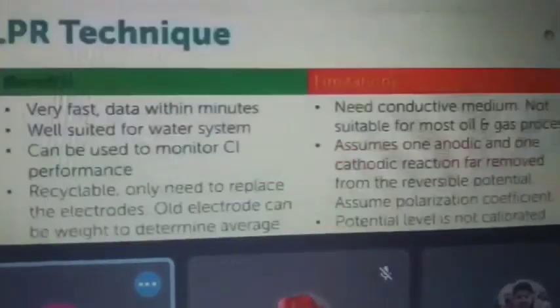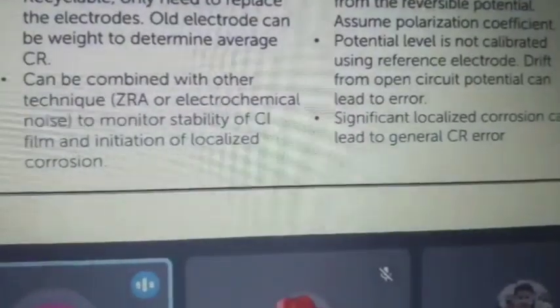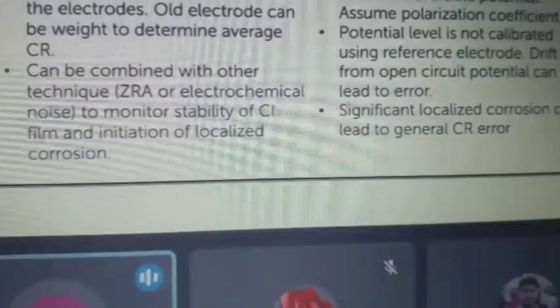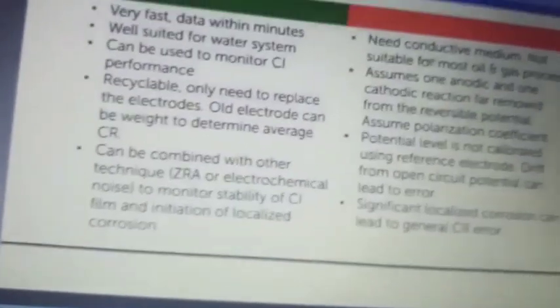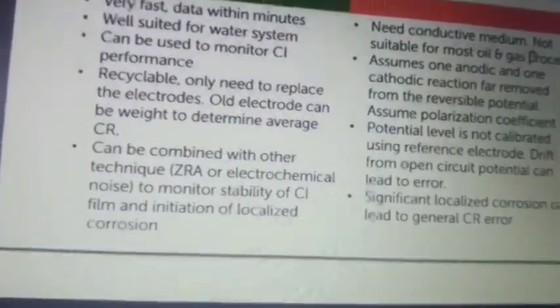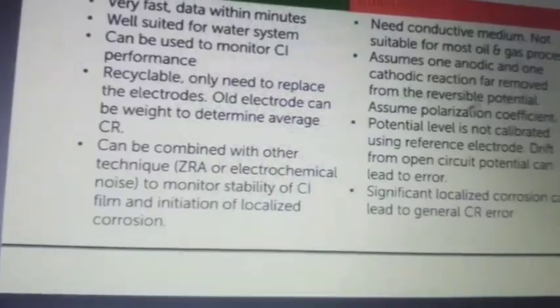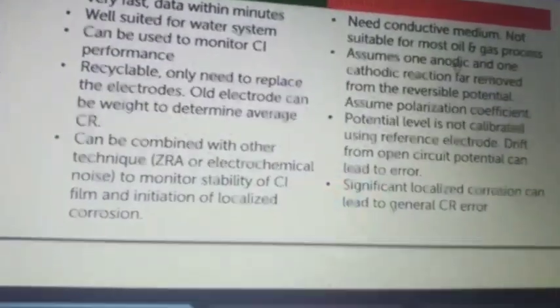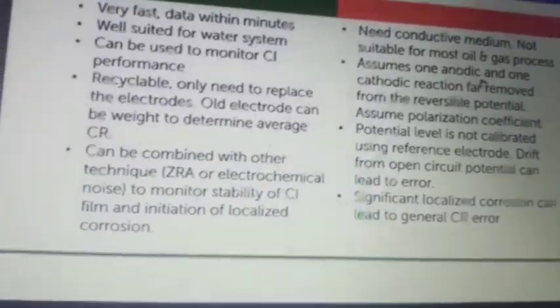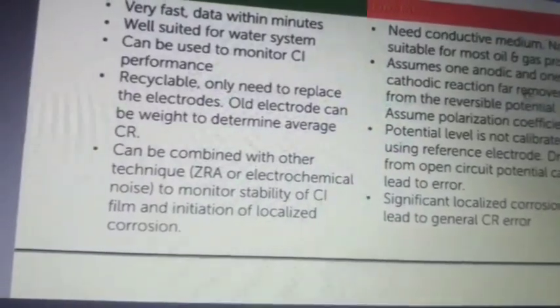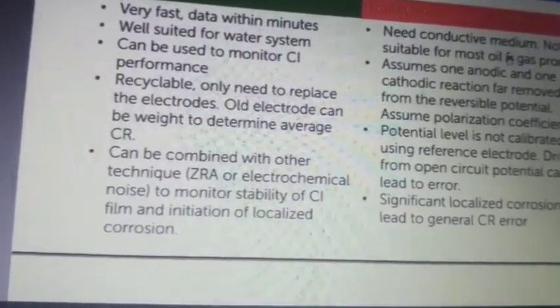The benefits are very fast data within minutes, well suited for water systems, and it can be used to monitor corrosion inhibitor performance. The limitation is that it needs a conductive medium and is not suitable for most oil and gas processes, because oil and gas streams have more oil or gas and sometimes less water. So basically we cannot use it in oil systems or gas systems.